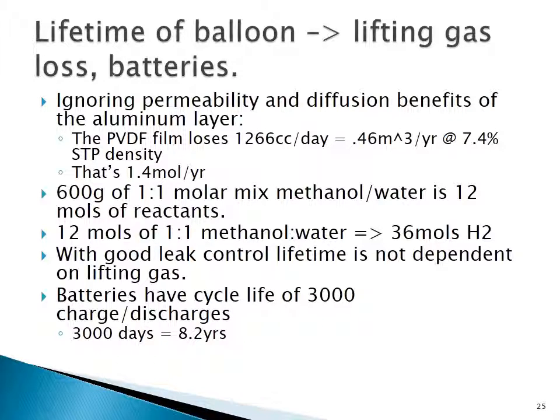Now the lifetime, as I said, the PVDF is pretty good for permeability against hydrogen and helium, and there's some backup slides that talk about this as well if you're curious. But the PVDF loses a little over a liter a day, so when you take into account that liter is at 7.4% of sea level density, that's 1.4 moles per year. Well, if you've got 600 grams of methanol water mix on board, that's 12 moles of reactants. It gives you 36 moles of hydrogen. And so in that case, you have over 25 years of hydrogen time essentially. So that gives you some nice margin over leaks.